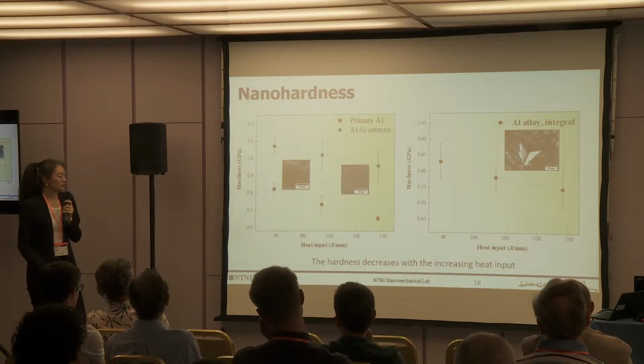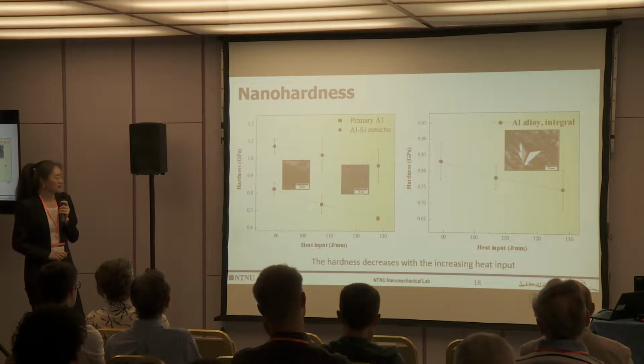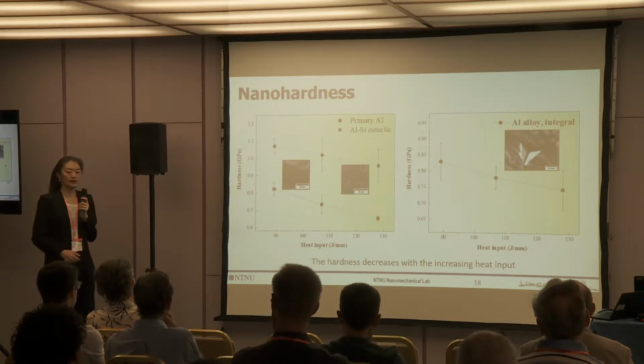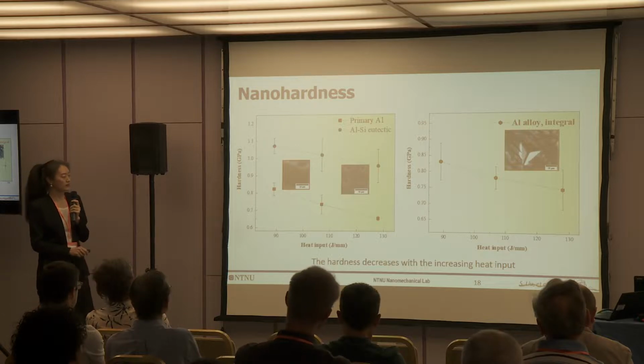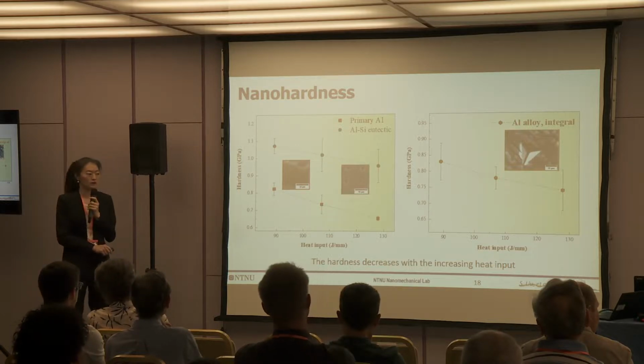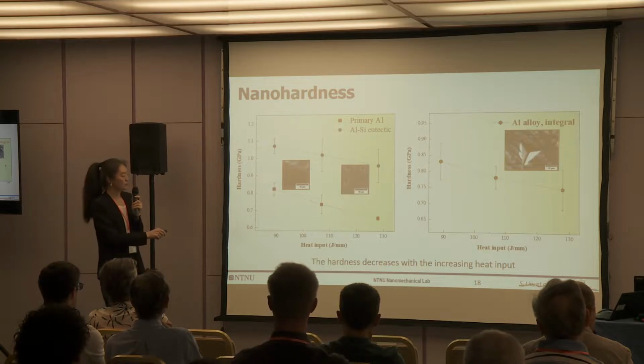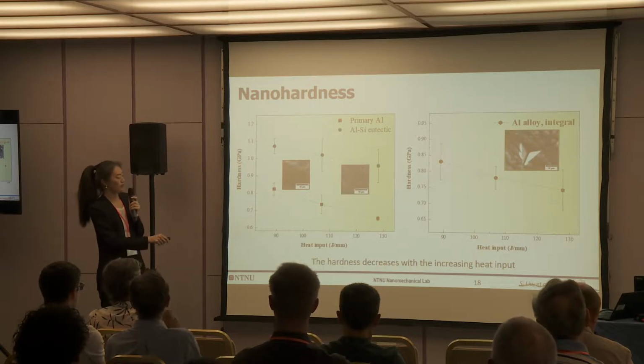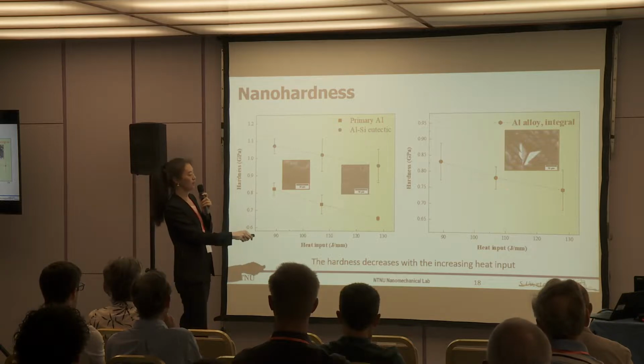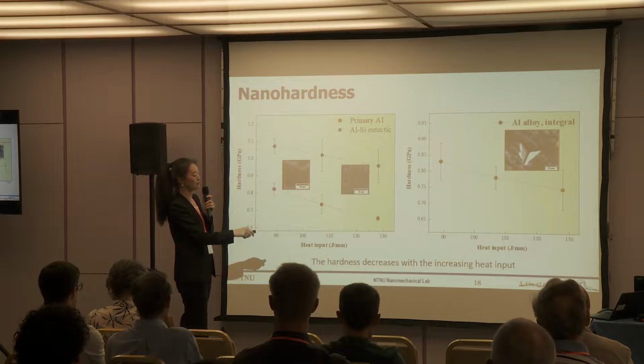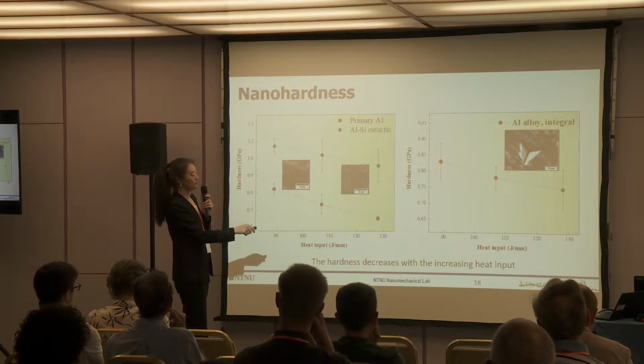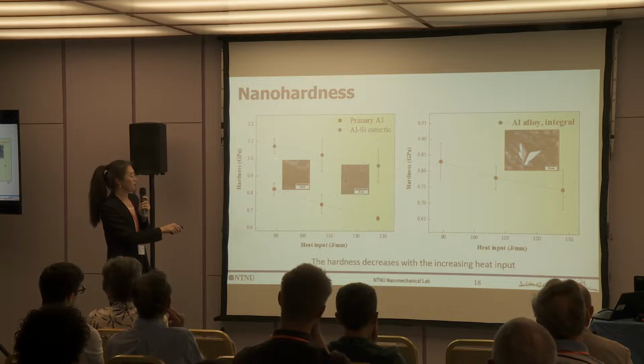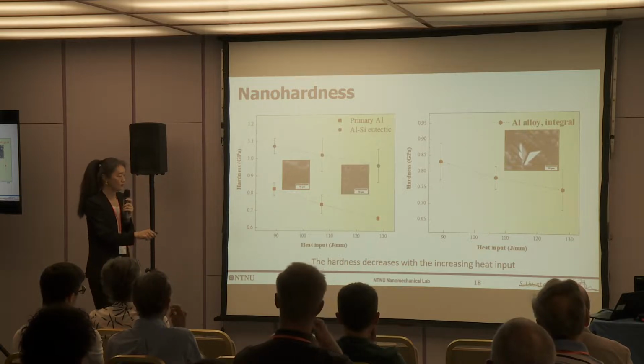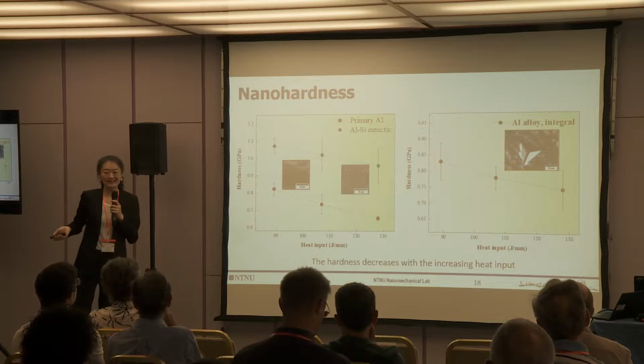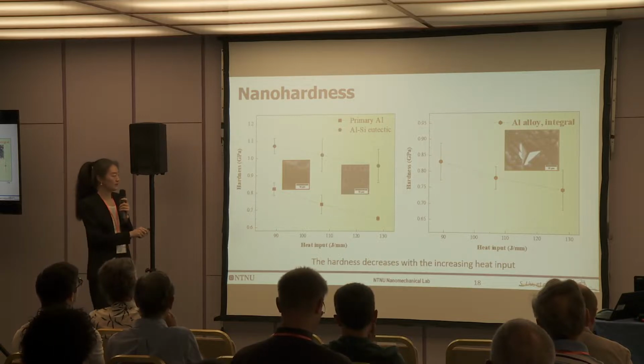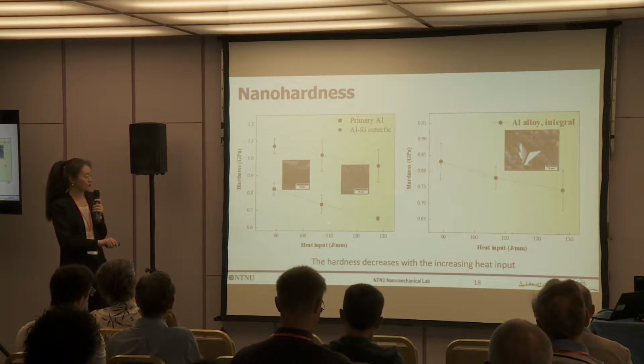Then we see the results. Also, we focus on the hardness. And we found a similar trend as reported in previous work, that is, hardness decreases with increasing heat input. If we test at the small scale, each individual phase, we have such behavior. And if we test at a larger scale, then we include quite a large deformation volume. We still have a similar trend. And also this integral testing result falls in the range between the primary aluminum and the eutectic phase. But now we only test the individual grain. And what dominates this hardness trend with the heat input?